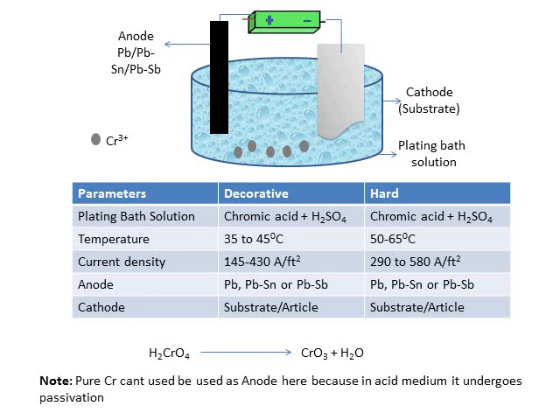So, how does the process actually take place? Chromic acid contains chromium in the +6 oxidation state in the form of chromium trioxide. These chromium +6 ions undergo a series of reactions and get converted into chromium +3 ions, which I have shown in the plating bath. These chromium 3+ ions move towards the surface of the substrate, where they undergo reduction and get deposited as chromium metal on the surface of the substrate. After obtaining the desired thickness, stop the plating process, take out the substrate which now has chromium metal on its surface, and use it for various applications.